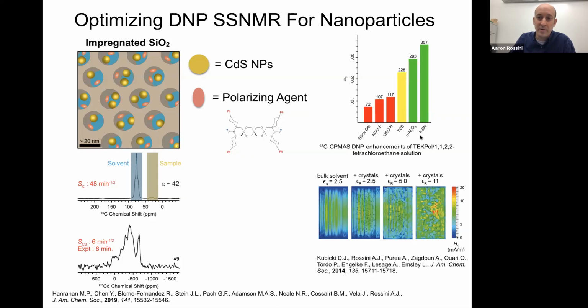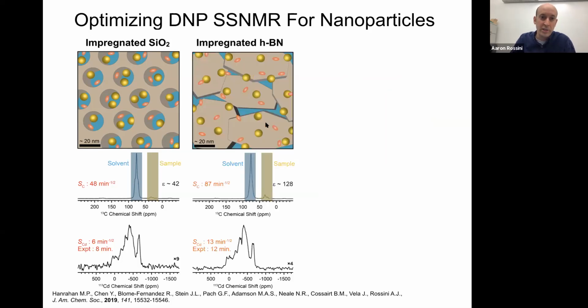So we screened a couple materials. We tried alpha alumina, which is actually sapphire, and hexagonal boron nitride. We observed that when we use hexagonal boron nitride, just impregnated with TEKPol TCE solution, we can get DNP enhancements of about 360. If you look at the dielectric properties of this material, you'll see it has a low dielectric constant. So if we just switch the material from mesoporous silica to hexagonal boron nitride to disperse these nanoparticles, we can triple the DNP enhancements, and this corresponds to a doubling in the absolute NMR sensitivity.